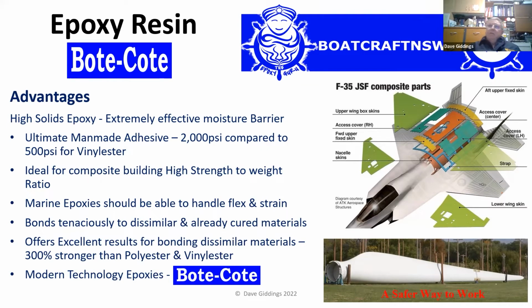It's about 48 MPa from memory. Some of the problem is when you go a bit higher in MPa, in your tensile strength, it starts to get brittle. But head and shoulders above epoxies that are made for holding bolts in concrete and things like that. Epoxy will stick to pretty well anything but your polyplastics. And even then you can cheat if you want, but don't. It's not worth the heartache.